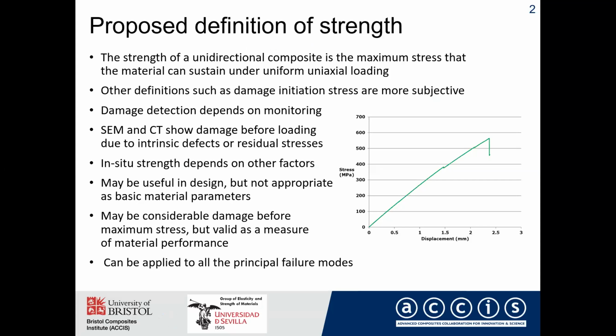Other definitions really could be much more subjective. And if you take damage initiation, for example, well, it's not very clear where exactly that is, and that depends on how closely you monitor the specimen. So Federico will say a bit more about this later, but if you look at that stress strain curve there, then I think most people looking at this would say straight away it's 550 megapascals, but if you look carefully, you see there's a little glitch at about 380, where actually the specimen was subject to some delamination. So you might easily miss that.